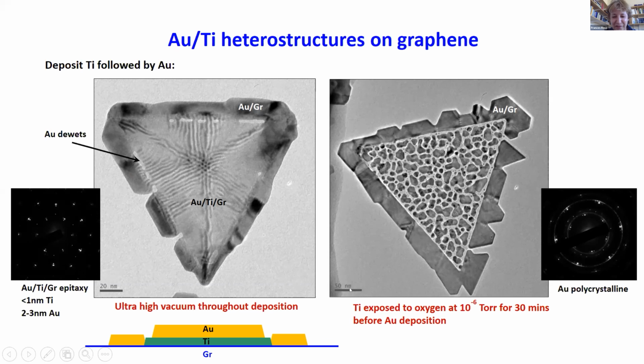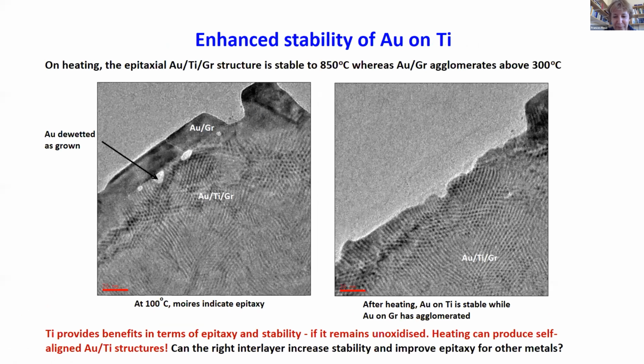But if we expose the Ti to a little bit of oxygen between depositing Ti and depositing gold, you can see that the surface has been oxidized. The gold no longer sticks epitaxially, it makes little islands, and the quality of the interface is very different. So this emphasizes the importance of doing these experiments in a very well-controlled vacuum, and also when you're doing processing in microelectronics, of controlling the deposition conditions very carefully. What we can also get from these images is a sort of self-aligned Au/Ti by removing the gold from the outside of the triangle.